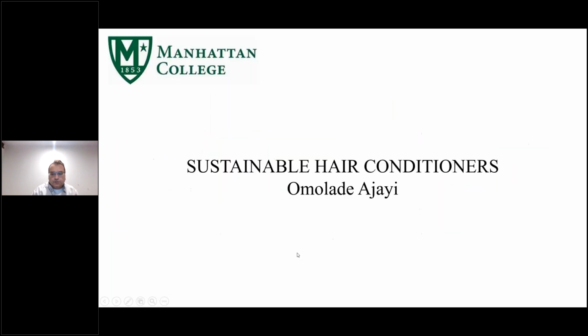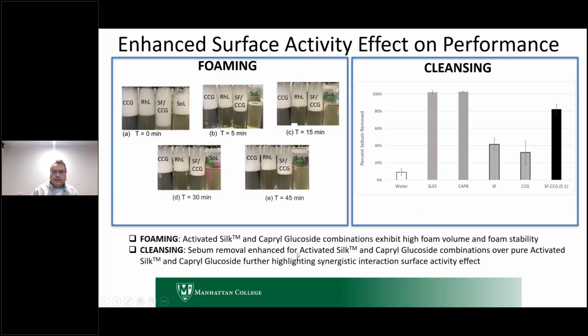We did cleansing as well. Sorry, and from that cleansing perspective, what we saw here is that again, we could get a system which was actually pretty decent in terms of percentage sebum removal. So good performance, beating performance in terms of foaming, very good performance in terms of cleansing. But the problem was this system was not viscous at all. It was still very low viscosity.